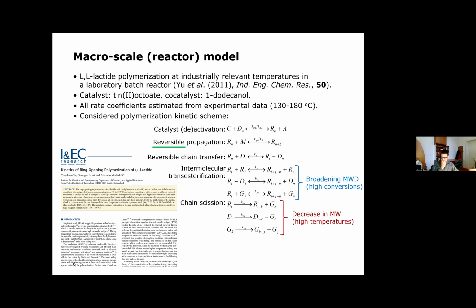And if you look at the proposed kinetic scheme, you may notice that most of the reactions are reversible, which I will address later on in my presentation. And there are some specific and important reactions which usually cannot be neglected, which is this intermolecular transesterification that leads to the broadening of molecular weight distribution at high conversions, and also random chain scission of polymer chains, which leads to the decrease of molecular weights at higher temperatures.